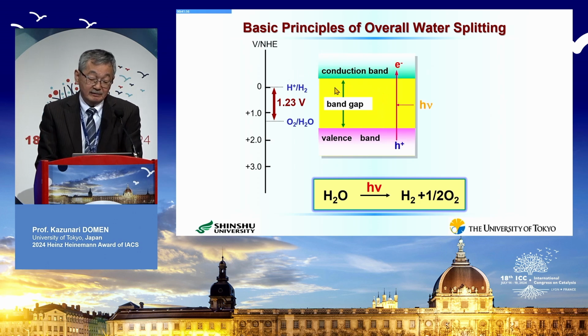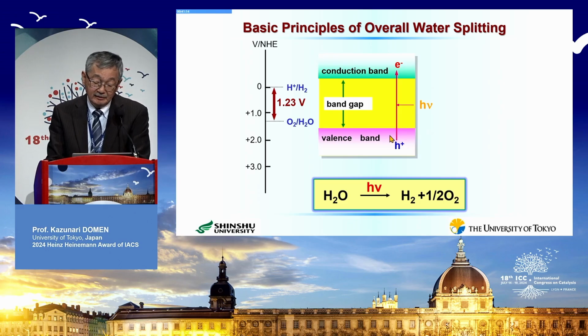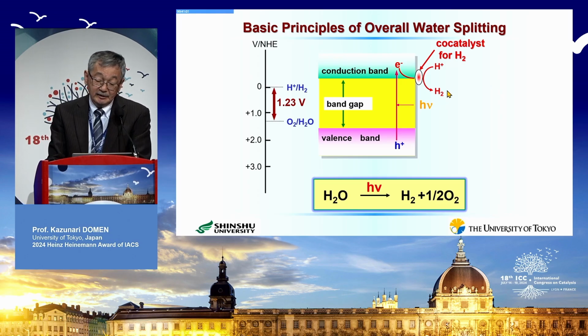Under photoirradiation, electrons in the valence band are excited into the conduction band. Then the conduction band minimum is located more negative than this hydrogen evolution potential. These photo-excited electrons are thermodynamically able to reduce protons into hydrogen molecules. But as long as we use n-type semiconducting materials, in almost all cases, we have to introduce a co-catalyst for hydrogen evolution, as shown here, to facilitate the electron transfer to protons and to generate hydrogen molecules.